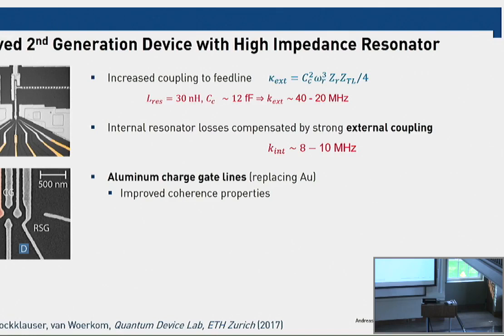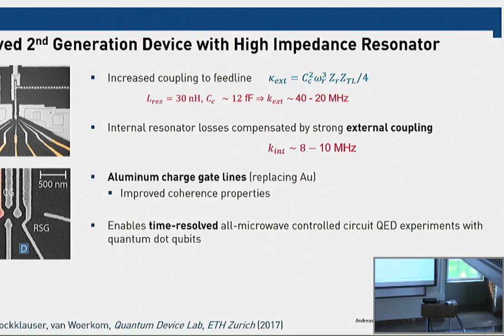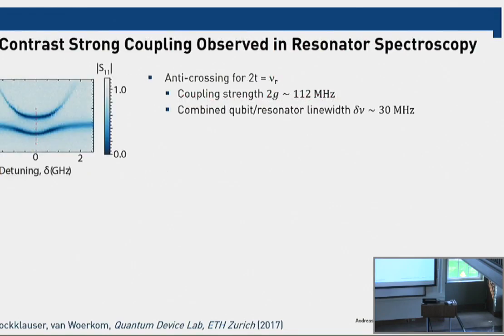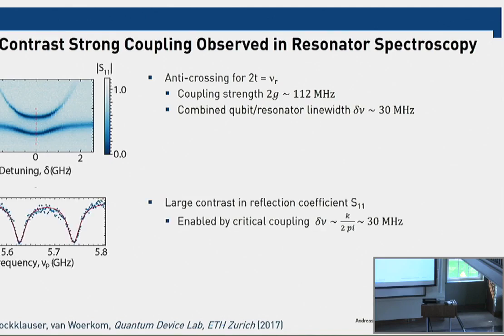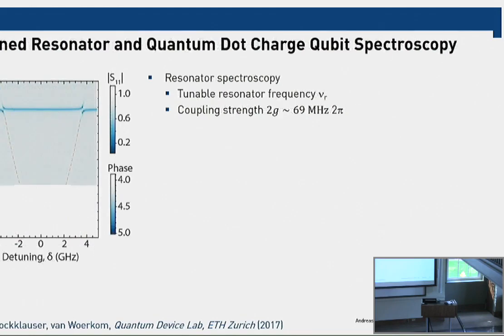And with these superconducting gates, we believe it's one of the contributors to really reduce the line width in the charge qubit by another factor of 10. And why that exactly is, I think there's maybe different thoughts about that I could comment on later. So with this improved device, here's another vacuum Rabi mode splitting where 2T is tuned into resonance with the resonator, and you see this vacuum Rabi mode splitting here. And now it's much nicer. The reflection signal from the cavity essentially goes down to 0 because the cavity is critically coupled. And so you get this very nice vacuum Rabi mode splitting here.